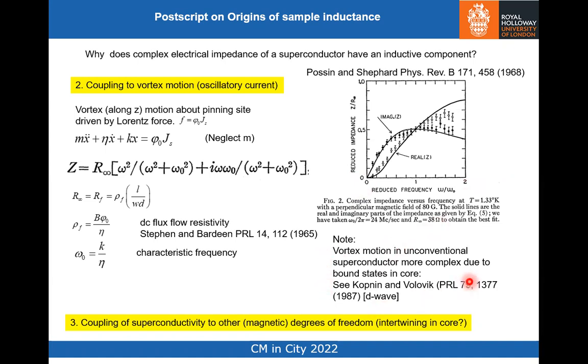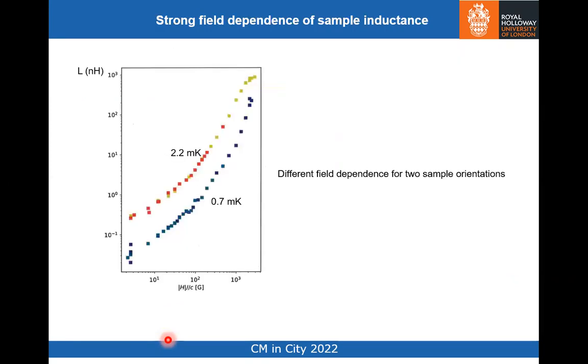But to note that if we're dealing with a spin triplet, or in general an unconventional superconductor, then there's all sorts of action going on in terms of bound states that the vortex causes, which is going to influence the dynamics of vortices. And I'll show you a plot in a minute. And the other possibility is that the superconductivity is coupled to other magnetic degrees of freedom, intertwined in some way. And so the upshot of that would be some inductive-like response.